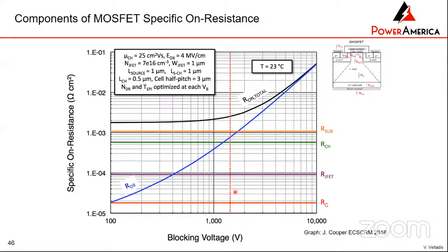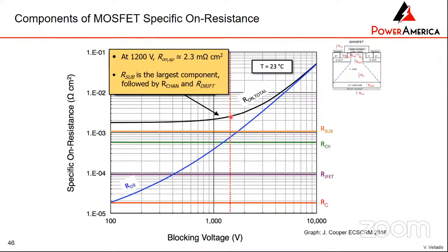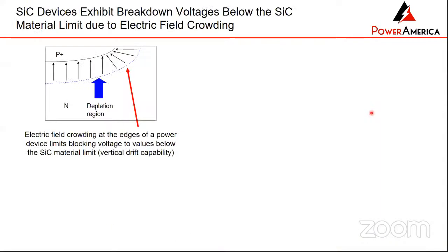So for the 1200 volt applications, which is a very major area right here, you can see that since the substrate is your biggest resistance, then you want to make the substrate thinner. You want to thin the substrate to reduce this resistance, and you have to be very careful in how you design your channel. You want to design your channel to be as low resistance as possible because it's still a big portion of the overall resistance. If you go to 10,000 volts, the substrate and the channel contributions are basically negligible, right? The big contribution at 10,000 volts, almost all of the resistance comes from the thick drift layer. So the bottom line is depending on the voltage rating of your device, you do the design of the device accordingly to reduce the resistance.